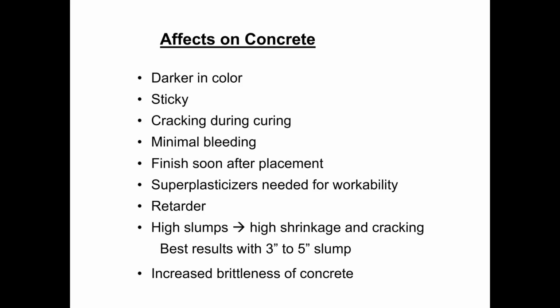Generally, high slump and silica fume do not go well together. The high slump is going to lead to a higher level of shrinkage and a greater potential for cracking. Usually a silica fume mix somewhere in the 3 to 5 inch slump range is going to be ideal. That's going to vary a little bit depending on the type of product that's being cast. But just as a general rule of thumb, if you would normally cast a given product at an 8 inch slump, then you may want to dial that down a little bit if you're using a silica fume mix just to help avoid some of these issues.